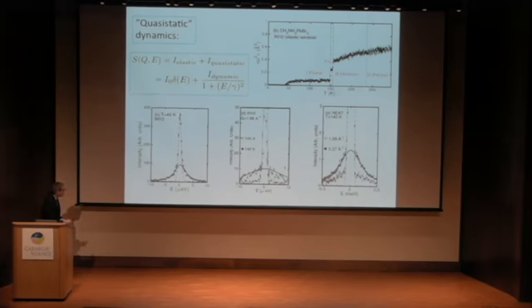What you can see from this scan is that there are two components to the scattering. There's this sharp bit, and the dashed line is the measured spectrometer resolution. So you see something that's elastic on the time scale of the spectrometer. But at the same time, you see this very broad component here. This fit here is a fit to this thing.